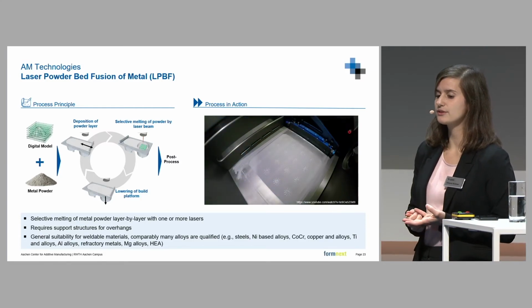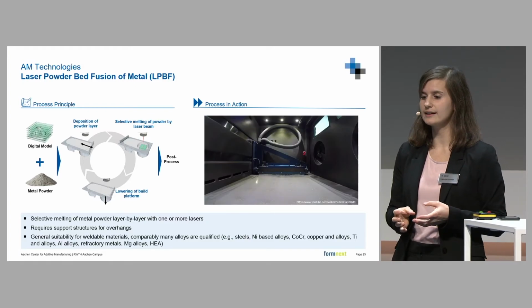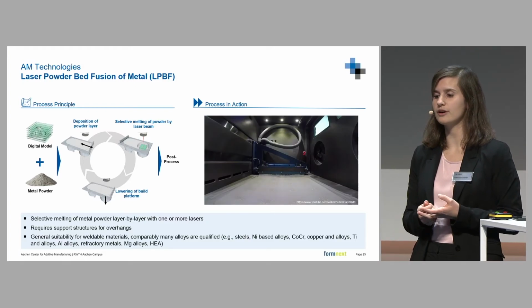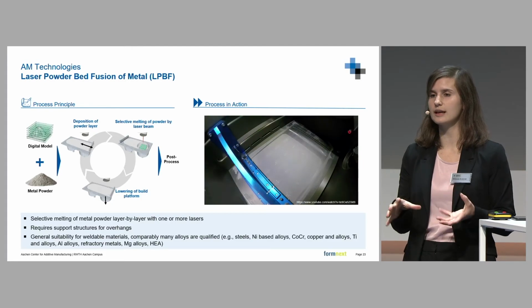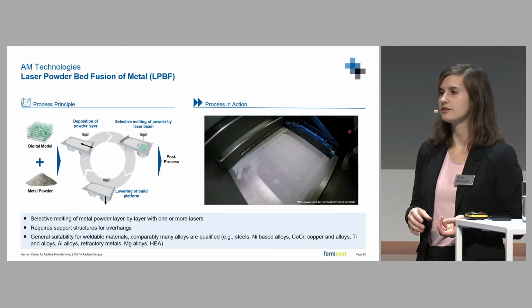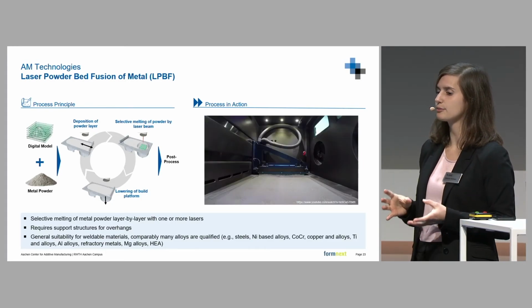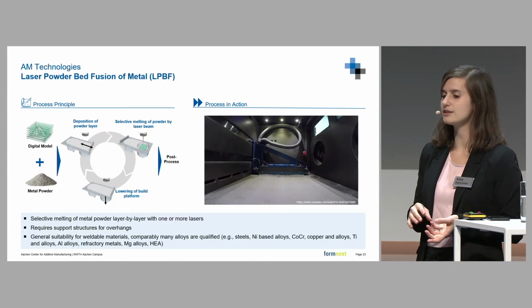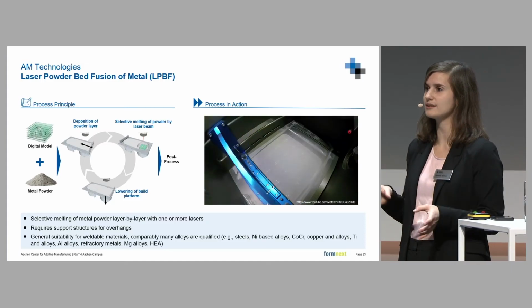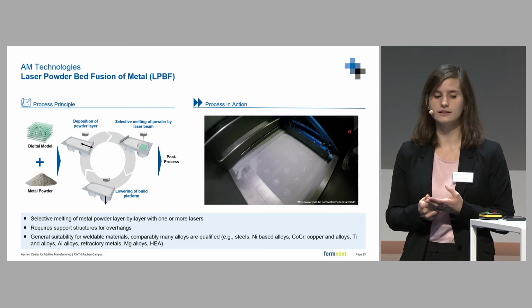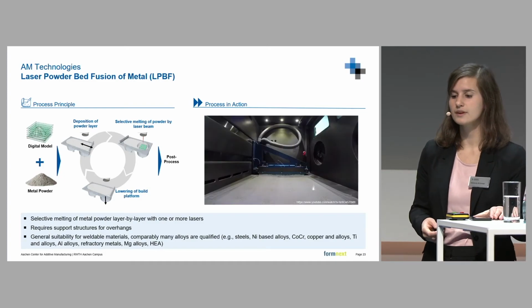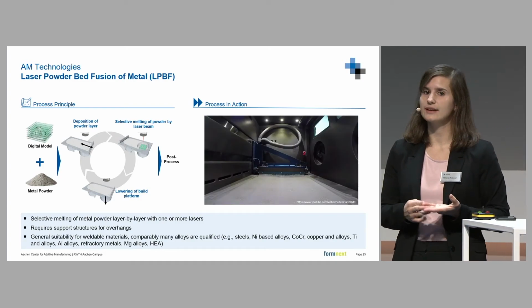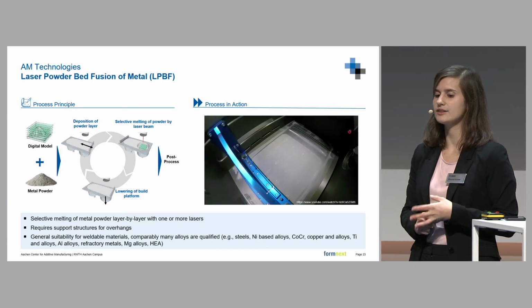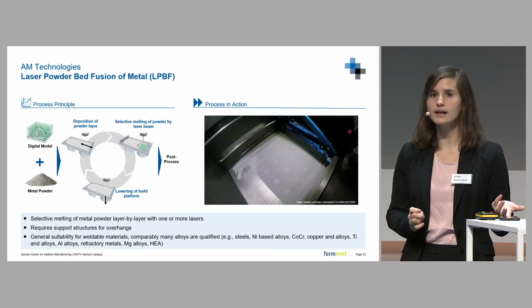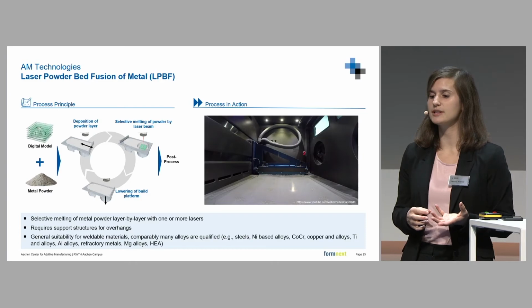Laser powder bed fusion requires support structures for overhangs, for heat convection, and also to stabilize the part within the powder. So you always have to make sure that you tie those parts physically to the build plate instead of just placing them free within the build chamber. One advantage of laser powder bed fusion is that it has a general suitability for weldable materials. So you have a very high material choice.